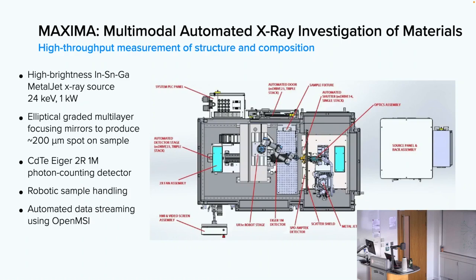And the reason that the brightness is important, and not simply the power, is we take that very small X-ray source size and we reflect those X-rays off of a pair of elliptically graded multi-layer mirrors. And it's those multi-layer mirrors now which are providing the focusing onto the small spot on the specimen. And so now our spatial resolution is basically 200 microns on the sample.